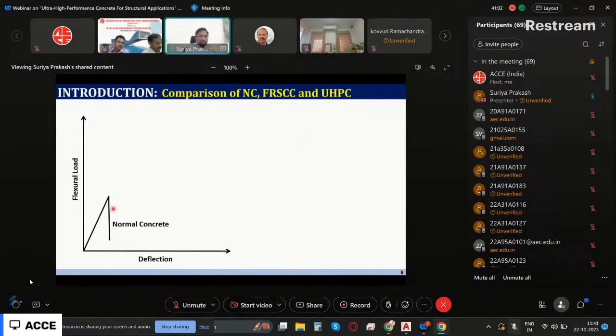Okay. So if I start plotting, let's say I cast a 200 mm by 200 mm beam and make it a length of, let's say, 1.5 meters, and then I put it in a universal testing machine and test it. You'll find the normal concrete will immediately crack, and it doesn't have any reinforcement. It'll fail like this. But if I have fiber reinforced self-consolidating concrete, fibers will increase your cracking load marginally. But even after cracking, it will not let it fall very suddenly. So you'll have a gradual fall like this. We call that strain softening behavior, because the load is not increasing after cracking. Okay? And in UHP FRC, again, you will have a very high cracking load.